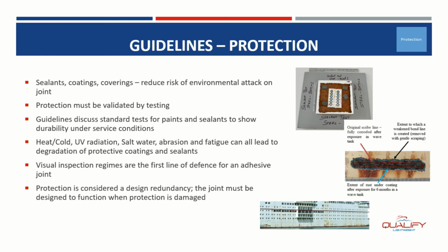The coating industry are also already familiar with this process and how we understand the effect of protection failure. The performance standard for protective coatings for cargo oil tanks and water ballast tanks has a lovely test that involves scribing a line into a coated sample, putting it in a wave tank and conditioning it for 6 months, either in water or oil, depending on the application. The idea is then when you take that out of the sample, you pick the coating away to see how far that bond is degraded between the coating and the steel.